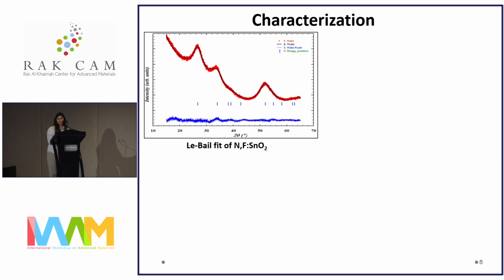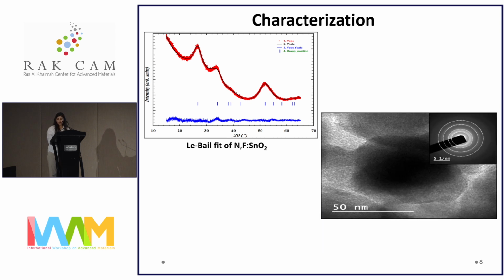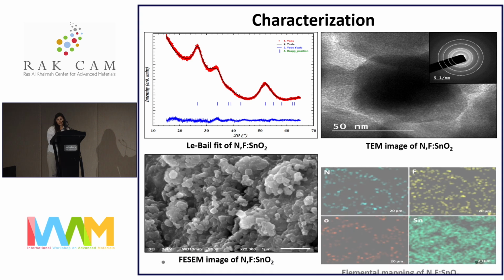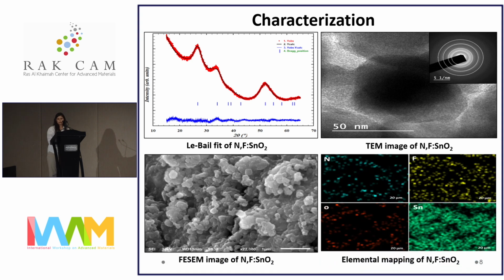Coming on to the characterization part, the very first one is the Le-Bail fit of nitrogen-fluorine co-doped SnO2. The powder XRD pattern depicts the rutile phase with tetragonal symmetry with the JCPDS file number 41-1445 with a space group of P42/mnm. The morphology and the elemental analysis were observed through SEM and TEM imaging. As we can see in the FE-SEM imaging, there is agglomeration of some spherical-shaped nanoparticles, which shows the doping of nitrogen and fluorine onto the lattice of tin oxide.